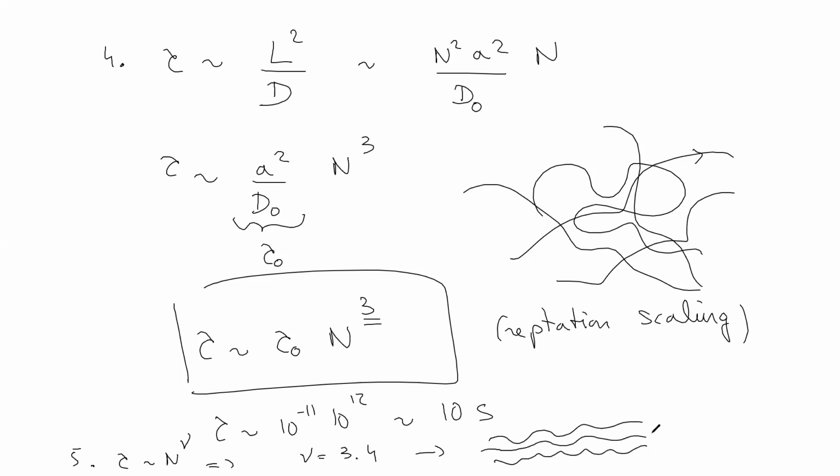The polymer chain is inside the tube, but the tube is made of other polymer chains that are moving, that are fluctuating. So you have fluctuation of the tube, and also the chain itself is fluctuating in these directions. So the tube also can extend longitudinally. So if you combine both effects, you can show that this leads to a fine correction of the exponent. But you got the main idea, and I let you have a look at the articles if you're interested in more details.